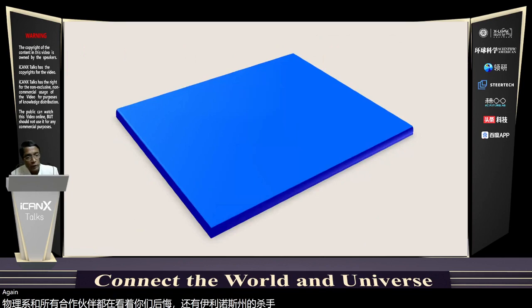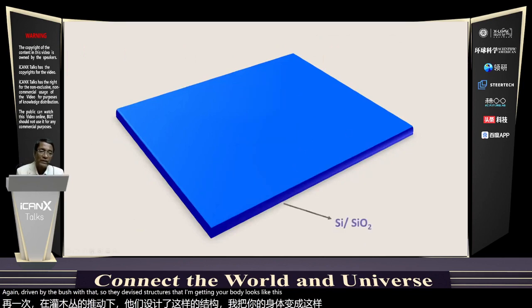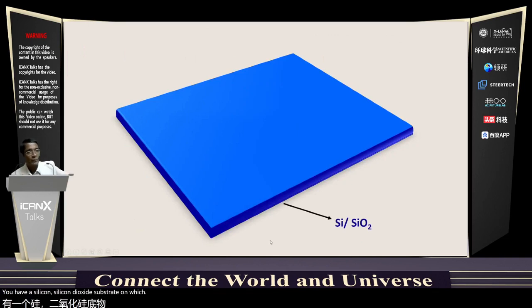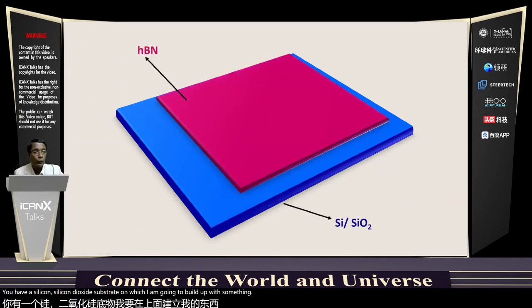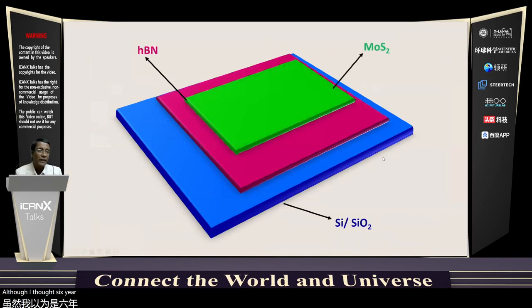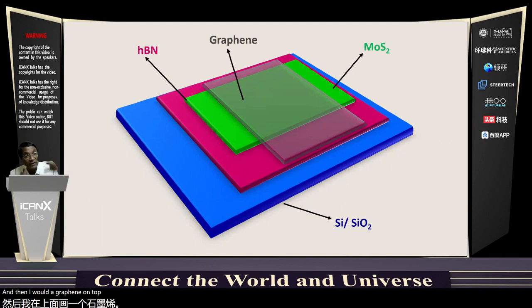Again, driven by Devoshmita. So the device structure that I'm telling you about looks like this. You have a silicon dioxide substrate on which I'm going to build up my sample. I put an hBN, which makes it absolutely neutral so that it doesn't couple to the otherwise substrate here. I lay down the molybdenum disulfide on top. And then I put a graphene on top, and this graphene is supposed to put a compressive stress on the system. And some part of MoS2 is not covered by graphene, some part is. Some part of graphene doesn't have MoS2.